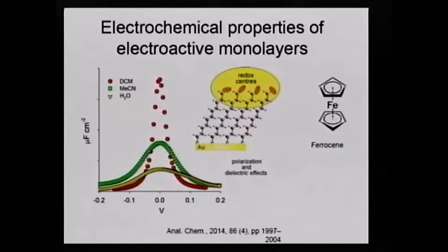And we see the capacitance changes because, of course, when you charge one group, it's difficult to charge the other that is around it. But this behavior also changes with the solvent. So again, you could say this is because the screening of this charge changes, so does the energy. And then we see this in the capacitance. But we see different fingerprints in here when we put more complex things. This is the first way the effect was seen, that the environment electrostatics could affect this communication.